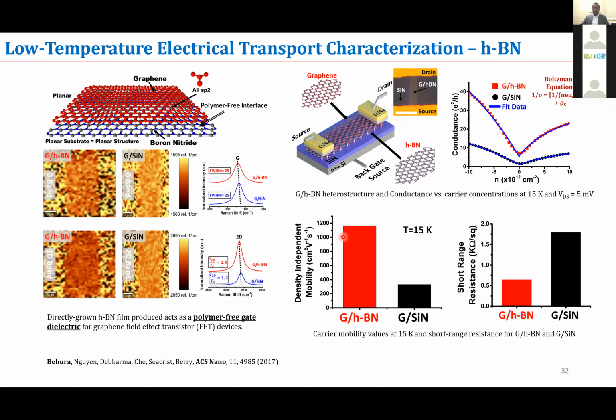And again, once boron nitride is formed, it is important to understand its quality. So we placed a layer of graphene on top of boron nitride, and we measured the electrical conductivity of the graphene on boron nitride. We found a charge carrier mobility of about 1200 centimeters squared per volt second when the graphene is sitting on the boron nitride structure, compared to graphene sitting on a silicon oxide or silicon nitride substrate. This is remarkable: it is how a two-dimensional Lego is formed, putting one two-dimensional material on another. Because boron nitride is atomically smooth and has fewer defects compared to silicon oxide, you can see almost three times higher charge carrier mobility for graphene sitting on boron nitride in comparison to graphene sitting on silicon nitride or silicon dioxide.